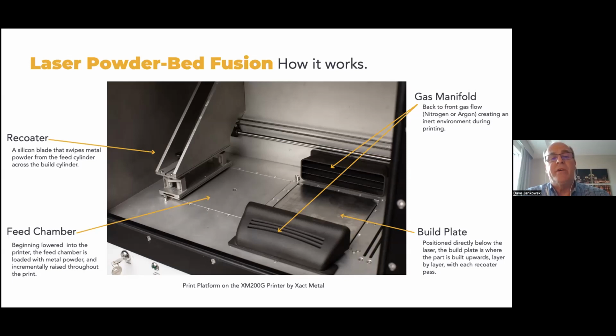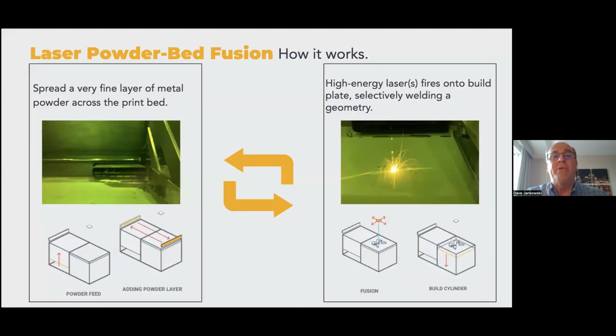So the left-hand feed chamber would be lowered. You would fill it up with powder. And then the recoater would move across the feed cylinder and take a very thin layer of powder. By thin, we're talking 30 microns approximately, and spread it onto the build plate. At that point, a high energy laser would then be activated to outline the shape of the component being printed. And then the process will be repeated hundreds of times, even thousands of times for some very tall applications. The real key to remember here is that the metal has to be weldable in order to be printable. Secondly, you have to use high quality powder that has a very narrow powder size dispersion. What we're going to show you next is essentially a more detailed example of the process being performed.